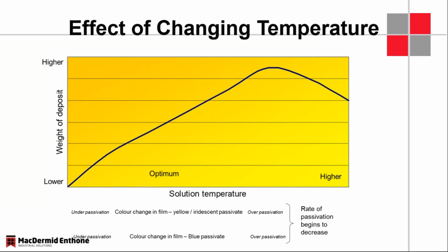Another thing about temperature, you can see this is the first graph that we've had that has almost a downward turn to it. And that is because as you are generating these Passivate films, what was I talking about in the beginning? I was talking about the chrome zinc complex. Well, what happens when there's no more zinc left and all you've got is chrome? You're not going to be building a film anymore. In fact, you're going to be stripping away the film that you had just put on there. With hexavalent chromates, that would lead to slough off. In this trivalent world, it leads to thinner film deposits and lower corrosion resistance.